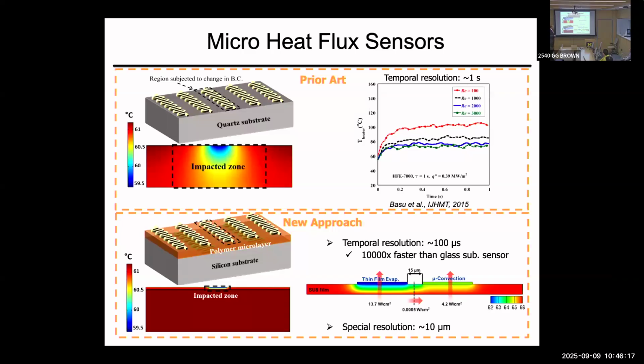So as I was thinking these long nights, I came up with a completely different idea. Instead of using a low conductivity substrate that everybody's using, I decided, why don't we use a high thermal conductivity substrate, right? And then have a very thin polymer layer all over the surface, and limit the temperature change only to that layer. So the thermal mass here is orders of magnitude less than the thermal mass here. Therefore, all of a sudden you can increase the response time by a factor of 10. So instead of all this region going through a temperature change, only this very small region does. The rest of it stays at a constant temperature. So that was really the beginning of being able to do the measurement.